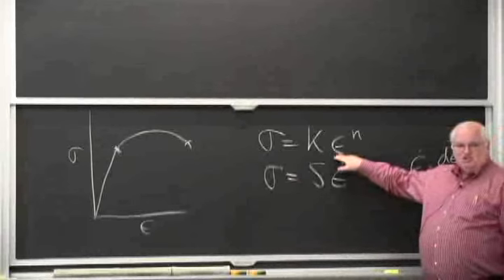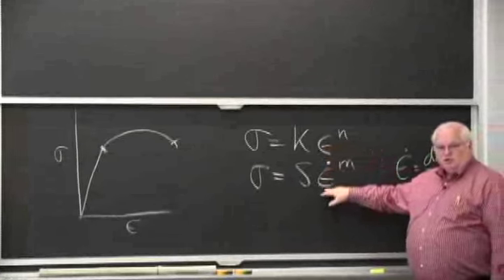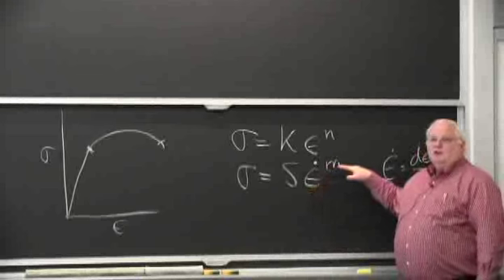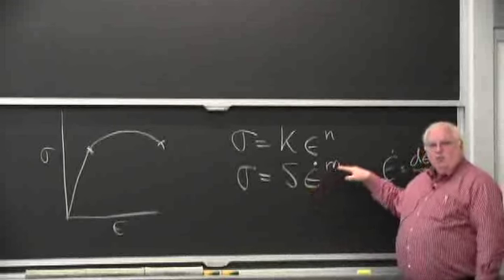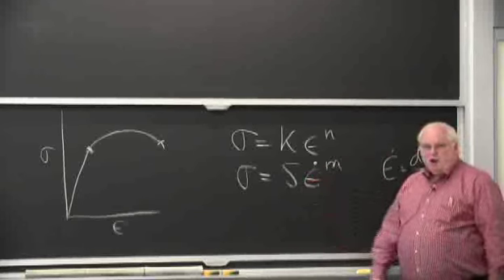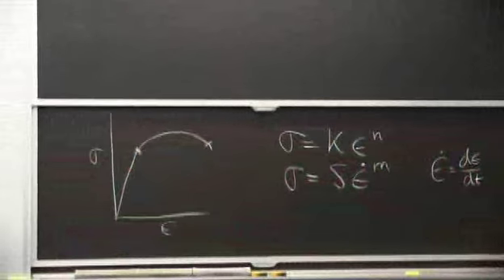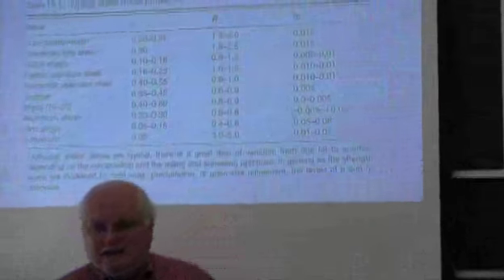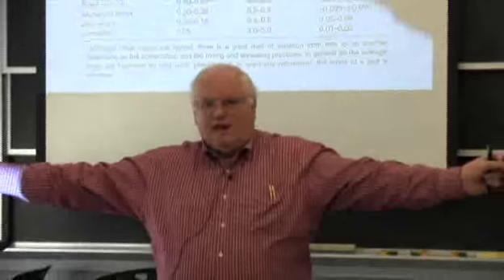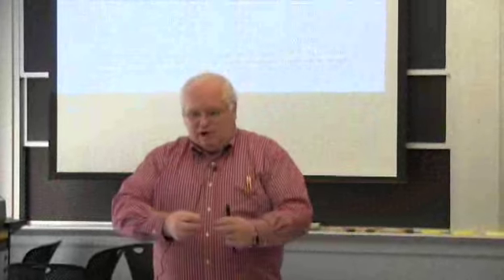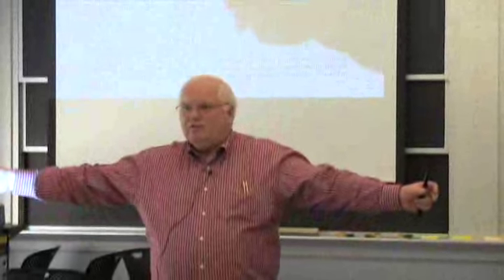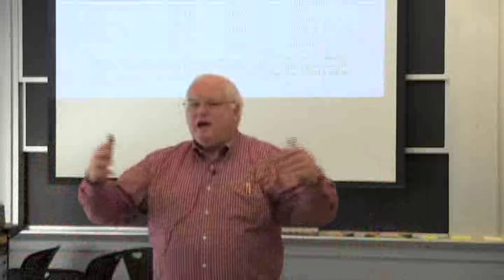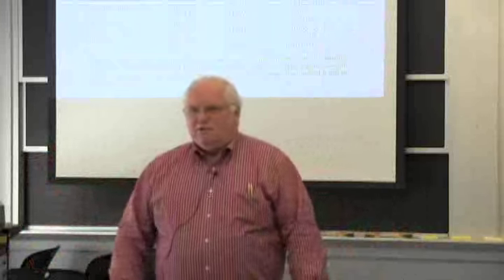So this is just the stress proportional to strain. This is the stress proportional to the strain rate. A Newtonian material has an m of 1. It's not dependent on strain rate. It will just pull and will not neck down. It'll just pull forever. He doesn't have glass up here. Glass has an m value of like 0.8, and that's why Corning can take these optical fibers and just pull them for miles in tension without a die, because whatever shape it starts out with, you can just pull it forever and thin it down. You can pull for tens of thousands, if not hundreds of thousands of percent, and you'll end up with something. If it started out uniform cross-section, it'll end up a uniform cross-section.